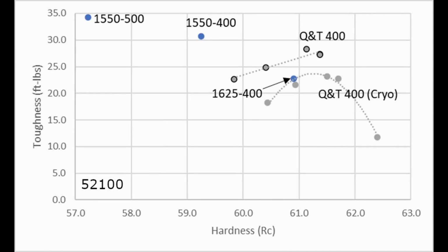But this goes to show that where bainite shines is usually in lower hardness levels than quench and tempered martensite, because if we wanted this same 57 Rockwell of the 52100 with quench and temper, we would probably have to temper at something like 500 degrees, which would be in the tempered martensite embrittlement range. So bainite can work really well when you want to get a little bit less hardness with higher toughness without worrying about tempered martensite embrittlement.